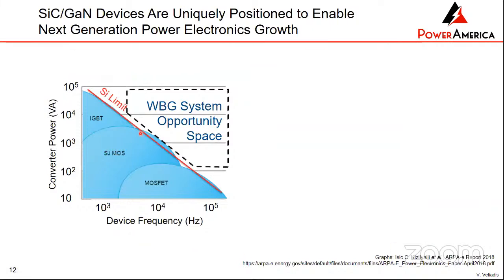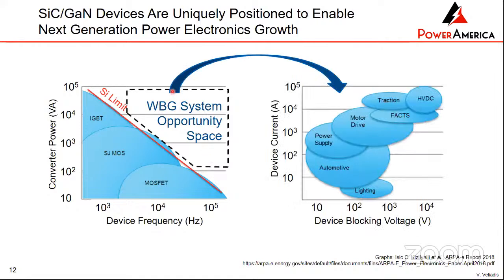So where do those advantages play a role? If you look at this graph, you can see that at lower frequencies, silicon does very, very well, and it's a very efficient material. Now, once you go beyond this red line here, meaning you're going to higher frequencies and high powers, that's where silicon carbide and GaN have a big opportunity to succeed because of their higher efficiency and because of the limitations of silicon. So what applications are in this high frequency, high power area? You have high voltage DC transmission. You have traction, which is basically what you're putting into electric vehicles, driving the AC motor. You have FACTS, motor drives, power supplies, lighting, and automotive. So there are a lot of applications in this space.